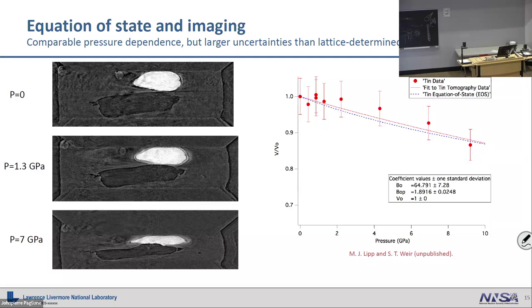And then here's what you have for the data. One thing you'll notice is the error bars are very large. X-ray diffraction error bars will typically be down below 1% or so. And these are clearly more in the several percent range. That's not surprising, because you have to figure out, just look at this picture, where does it end? Is it the inside or the outside? Make a choice and put an error bar on it.